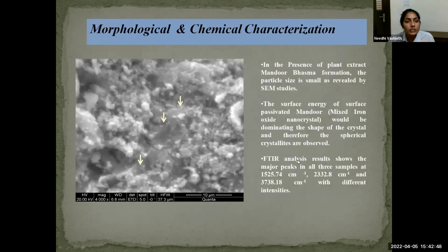Now moving to the next, morphological and chemical characterization. In the presence of the plant extract, in Mandur Bhasma formation, the particle size is very small by SEM, that is scanning electron microscopy, as we can see here. These are very small particles. The surface energy of the surface-passivated Mandur mixed iron oxide nanocrystals would dominate the shape of the crystal, and therefore spherical crystallites are observed.